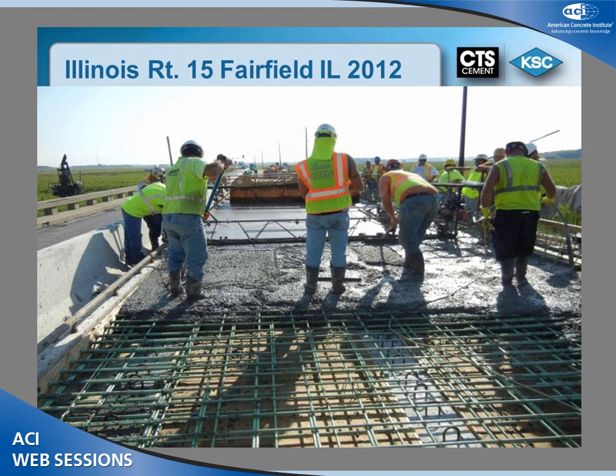And some people say it's the first time we've done it in Illinois. No, this is not. We actually did several bridges back in the 90s that, upon survey in 2010, were found to have no cracks and in pristine condition. However, the state of Illinois decided they wanted to revisit this with a redesign, so to speak, and they did not accept the mix designs or the specifications from Ohio and Michigan, and set out to come up with some of their own new specifications.